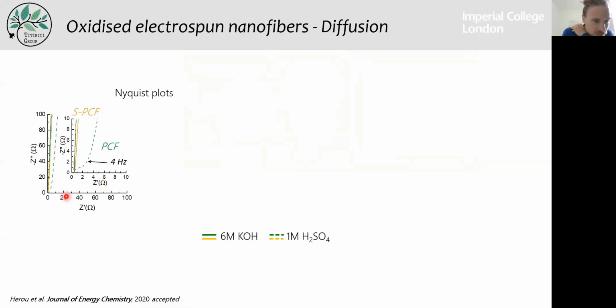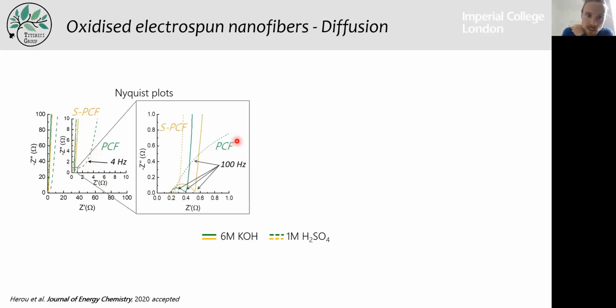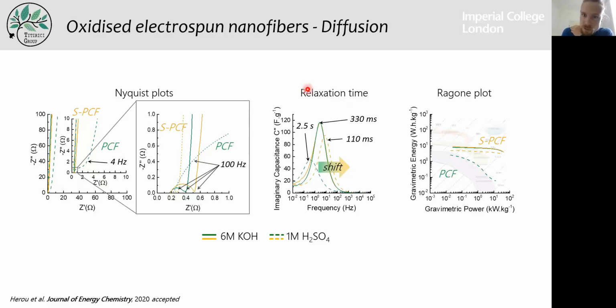So here the Nyquist plot is showing that in the case of acidic conditions, your non-stabilized sample basically shows exactly this diffusion limitation. And that is why we have really poor performance in acidic conditions. Here, if you look at the relaxation time, that tells you basically how fast you can charge and discharge your device. And here you observe with the plain lines that you have the same relaxation time in basic environment, but much faster relaxation time in acidic environment.